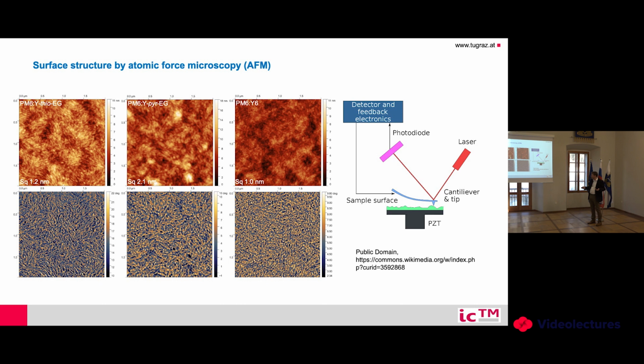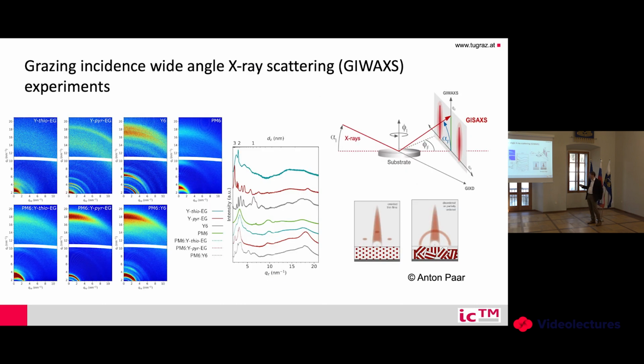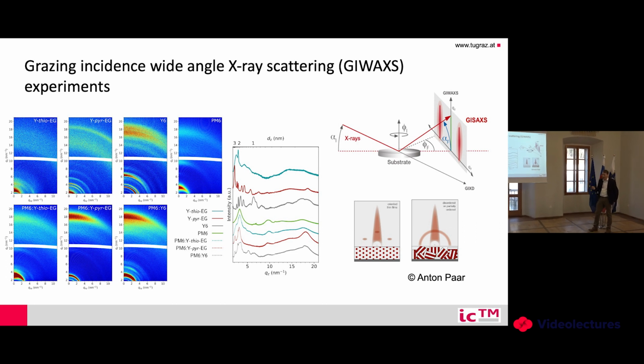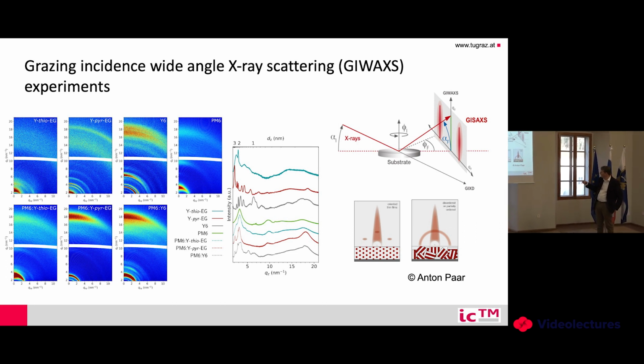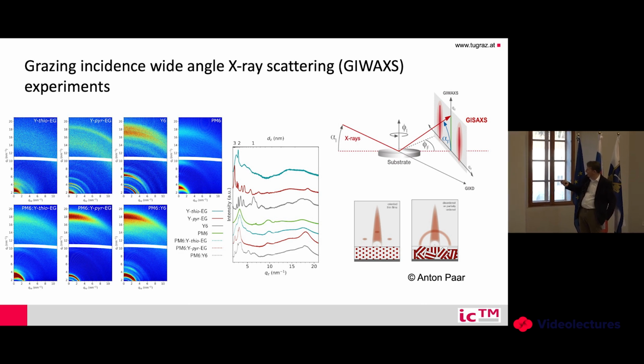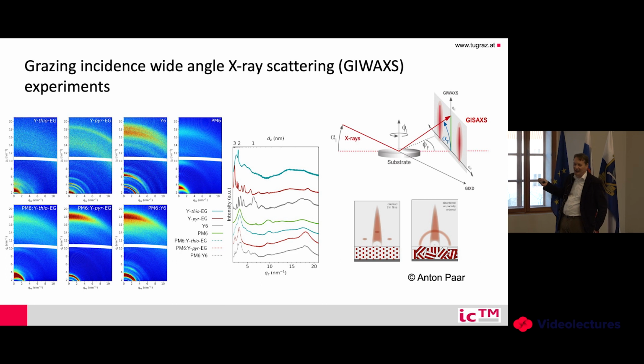We also investigated even more. So we have also studied by grazing incidence wide-angle X-ray scattering. So what you're doing here, with an X-ray beam, at a very special angle, you shine X-rays on your substrate, and you measure the scattered light, like in a classical crystallographic experiment. And depending on what type of structure you have, you get different signals. You have a 2D detector, and these are the different materials. So you see some differences. You see that you have perhaps a little bit higher orientation or higher crystallinity in our material, but not that large, especially if you're also looking at the electron microscopy images, which are shown on the next one.